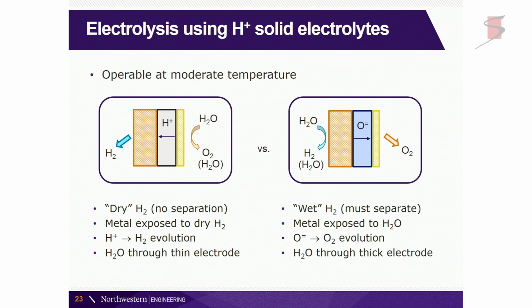So our air electrode is the one that's being exposed to steam. In this case, this material is very happy. It's an oxide. It has no problem with seeing a whole lot of steam. In the case where you were using an oxygen ion conductor, you have all this nickel, which is still serving as a support, and if you supply it with steam, it just is not very happy. And so degradation in this system is quite severe. There are other aspects here, so that the fuel that you produce here is just dry hydrogen, essentially, whereas here it is generated along with the unreacted steam, so you may have to do a separation step later. That's not so costly because removing steam is not so hard, but it is an extra step.